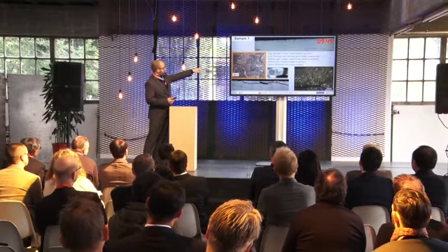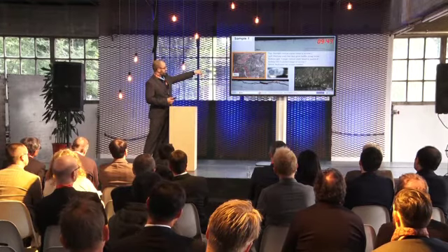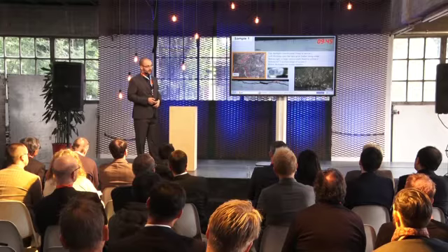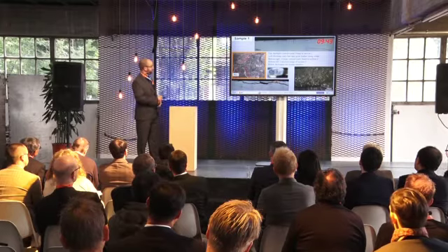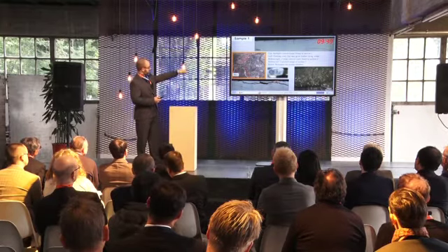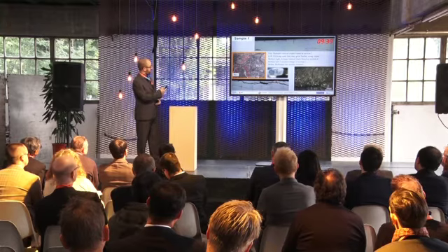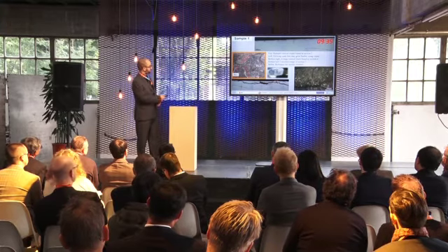And you can see how the crack would naturally like to continue to follow this ferrite that's segregating out due to the thermal damage. So this is why I believe studs are growing faster than squats, because these natural pathways are making it very easy for the cracks.